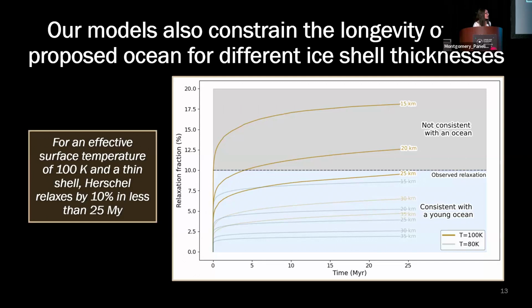First off, I just wanted to say we did calculate tidal stresses throughout the evolutions of those thinning ice shells in the 2024 paper, and they're still only hundreds of kilopascals. So the tidal stresses will not dominate over the compressive stresses, even with higher eccentricities. But my question is, it seems like you've made an assumption in your study that if you have compressive failure, you will have surface features. Is it possible that the compressive failure begins in the subsurface, and so the surface manifestation is simply not as obvious or perhaps more diffuse?